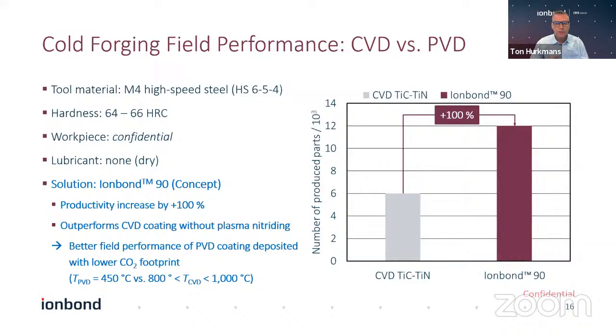Another example, away from cutting applications, more into forming tool applications. Here we see an example where we use PVD technology over a CVD. CVD stands for chemical vapor deposition, and it's a very high temperature process. 800 to 1000 degrees or even up to 1200 degrees Celsius is the typical processing temperature. We found a coating solution by PVD. On the right hand side, there's a trade name, Ionbond 90 in this case, where we saw also a factor 2 of an improvement over the CVD.